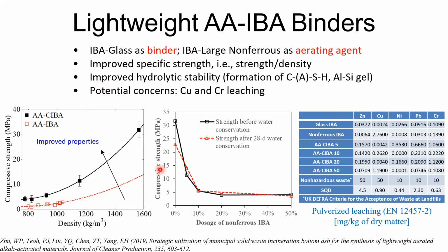Mechanically, we can clearly show that the resulting aerated concrete, using glass as the matrix and large non-ferrous particles as an aerating agent, shows a much improved compressive strength versus density ratio, shown by the black curve here.